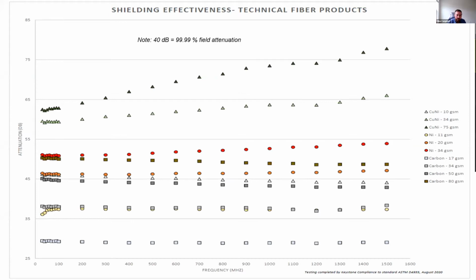So this here is some ASTM D4935 testing. It tests from 30 megahertz down here on the left side of the domain and up to 1.5 gigahertz. I like to point out our nickel coated carbon veil, which is the red circle here, at 34 grams per square meter. So still pretty light. And that gets you around 50 dB testing at the low end there and up to 55 dB at 1.5 gigahertz.